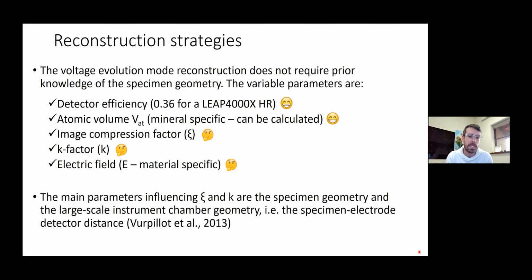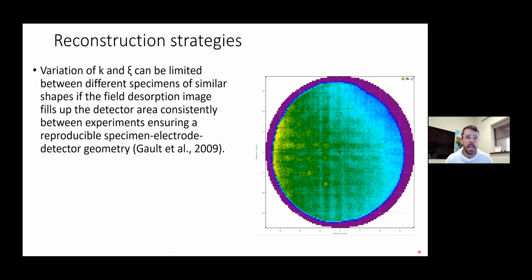The thing we know though is that the main parameters which influence the image compression factor and the K factor are the specimen geometry, but also the large scale instrument chamber geometry. So in other words, the specimen, electrode and detector distance. It is thought that these variations can be limited between specimens of the same shape if the field desorption image fills up the detector consistently between experiments.